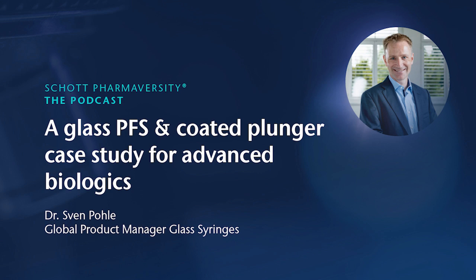RNS and plunger are elastomeric components, each with a complex profile of properties. For the rigid needle shield, it is important to assess the fitness for intended use. So the application of biologics requires a high quality extractables and leachables profile. That means low levels of extractables and leachables to reduce the interactions with the complex drug to a minimum. Moreover, the RNS is permeable. I mentioned that before already, to enable sterilization of the empty syringes, leading to the ready-to-use concept of today's prefillable syringes. This permeability comes with a certain oxygen and water vapor transmission rate. There are different RNS in the market, and they all have different properties in this context. And here, our consulting continues, and we recommend to our pharma customers the right solution depending on the drug requirements.